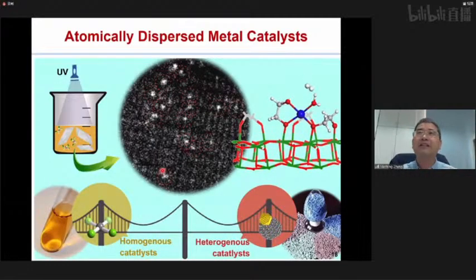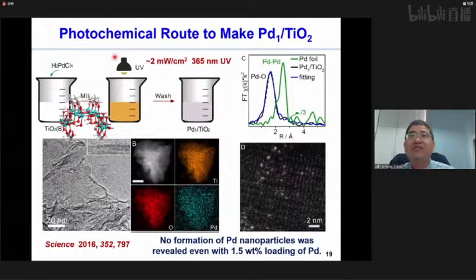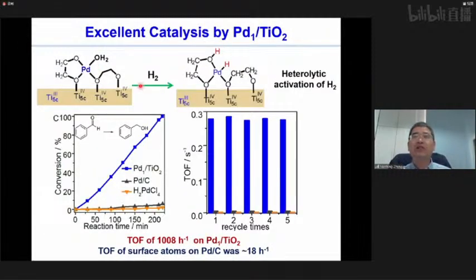Another model nanocatalyst is the atomically dispersed metal catalyst. Several years ago, we developed an effective photochemical method to prepare atomically dispersed palladium on titanium oxide. All these palladium sites are atomically dispersed on the support and have uniform coordination environments, so we can use X-ray absorption spectroscopy to identify their local coordination environment. After the fitting, we found that the palladium is four-coordinated and is bound by ethylene glycolate together with waters.